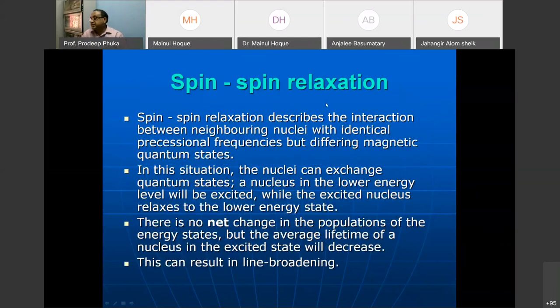Then this is spin-spin relaxation. Actually, in this case, there is just a transfer of energy to the neighboring nucleus. Spin-spin relaxation describes the interaction between neighboring nuclei with identical precession frequencies but different magnetic quantum states. In this situation, the nuclei can exchange quantum states, and a nucleus in the lower energy level is excited, while the excited nucleus relaxes to the lower energy. There is no net change in the population of the energy states, but the average lifetime of a nucleus in the excited state will decrease. So this will result in line broadening.